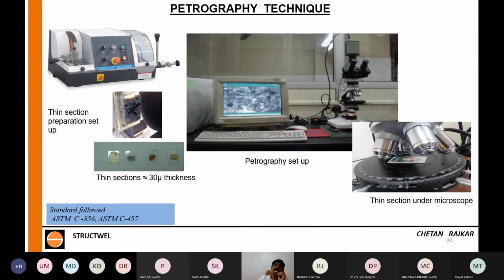The stone and concrete actually become transparent depending on the ingredients. Then you see it under a microscope at 50 times magnification, 100 times magnification. And this instrument, what you see here, is a thin section preparation set. But this sample can be prepared by hand also. This equipment is prohibitively expensive, but if you have people who are trained, it can be done by hand with a very locally manufactured machine. But you need a good quality microscope, and this is how you see on the screen.